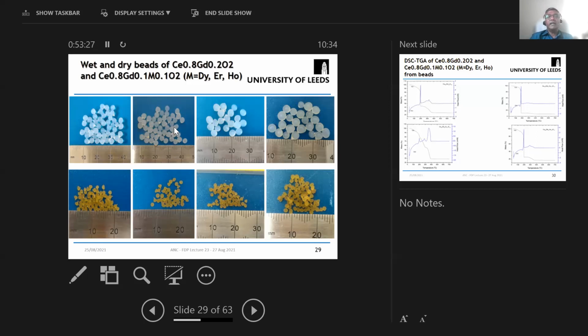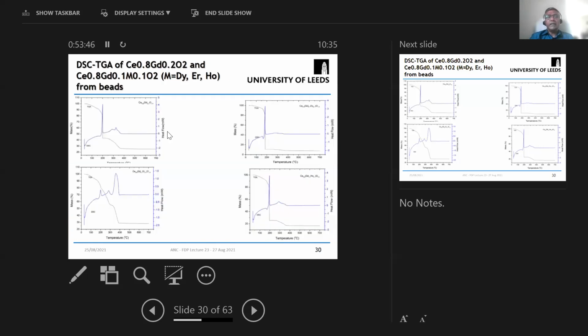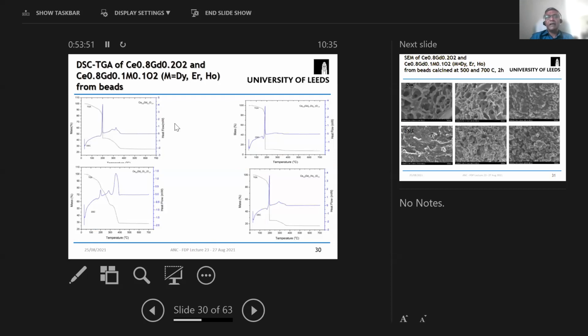And that is the reason why they're highly porous, as seen by the X-ray microtomography images earlier in the talk. So these are highly porous, and therefore they successfully yield the nanopowders. So we did the DSC TGA. These are the standard DSC TGA graphs, basically to find out what is the minimum temperature at which you need to calcine these powders or these beads to produce nanopowders. So you can see that the calcination temperature is somewhere around 400 for all these four different compositions. That is cerium gadolinium oxide, and then cerium gadolinium oxide co-doped with dysprosium, erbium, and holmium.